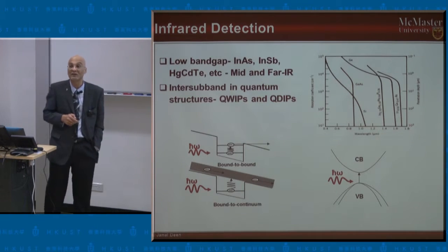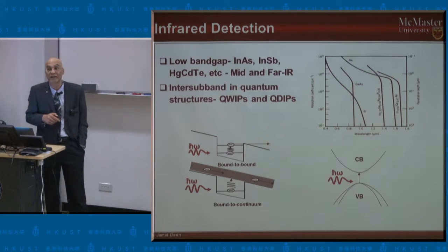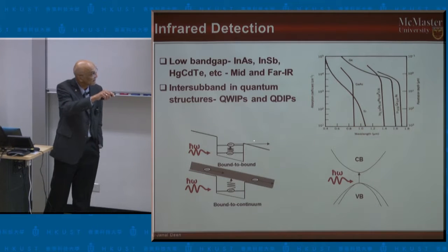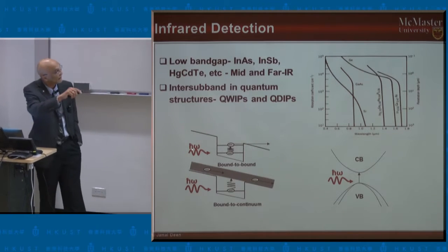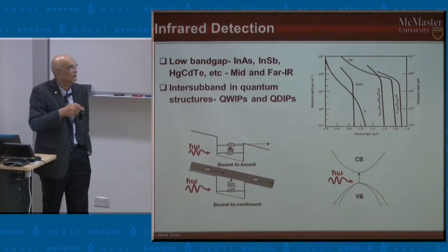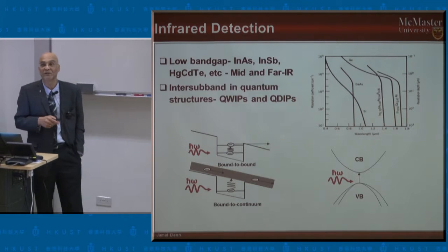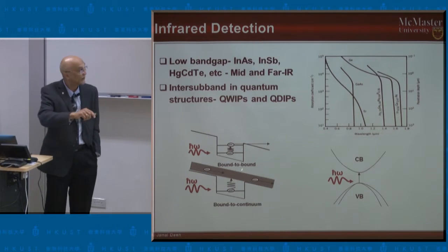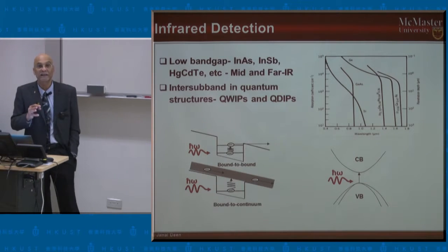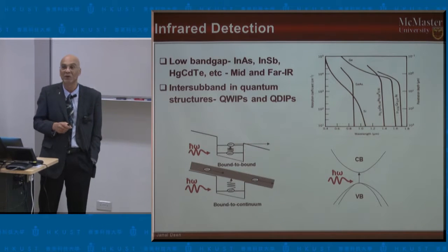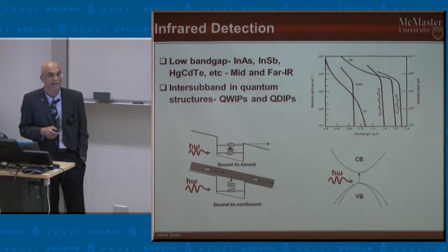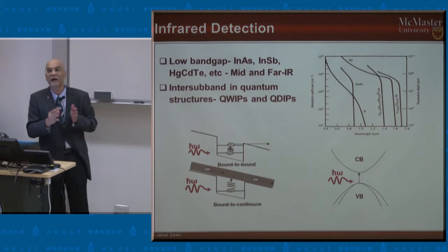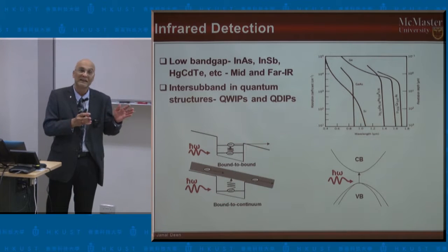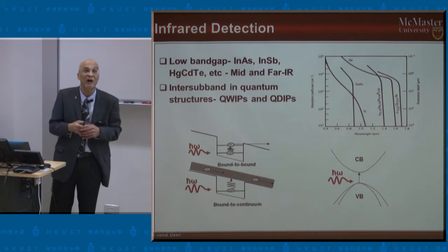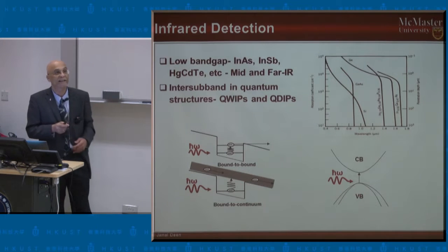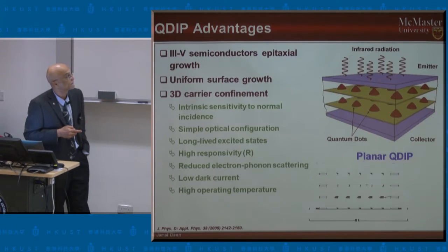We can also exploit bound to bound. So here we have charges that are trapped at one bound level within one of the band edges, and it can get excited to a different localized level, in this case in a quantum well, with light of an appropriate wavelength. So we can have a bound-to-bound transition. The range of wavelength over which these III-V semiconductors operate exploits both bound-to-bound and bound-to-continuum transitions. By exploiting these phenomena, we can have a very wide wavelength range of response, from visible all the way to medium wave infrared and even long wavelength infrared, for many applications, again mostly in the environmental area and in the biomedical area.